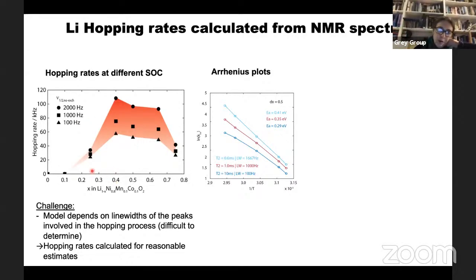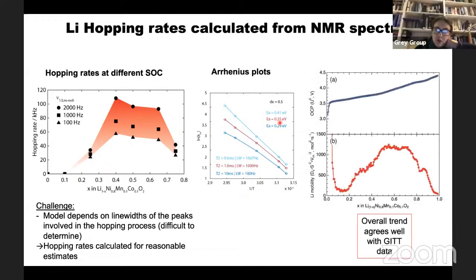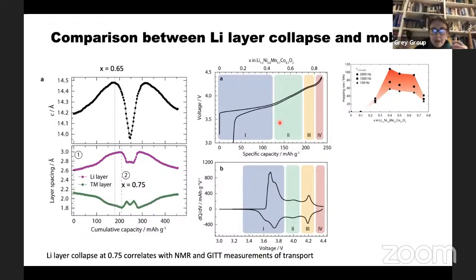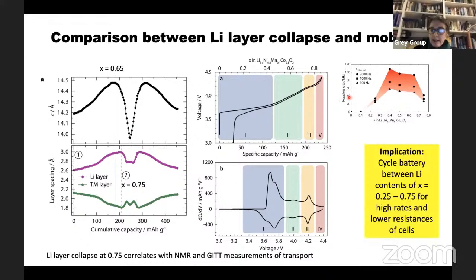And what you see is between about 0.25 and 0.75, you get quite rapid lithium ion conductivity, and you get moderately low activation barriers for transport. So this is all good if you want a fast charging battery. And this also agrees with electrochemical measurements we do. And so then you go back to this question that motivated it. What happens when you get this layer collapse? And remember, the layer collapse is happening at 0.75. That's in the same region where you get this reduction in lithium mobility. And so the take-home message from a car manufacturer's perspective is, if you want a high-rate battery, then you need to cycle between 0.25 and 0.75.